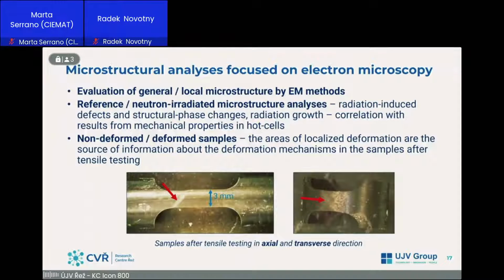And going to the microstructural support, which is focused on electron microscopy studies, this is like the last part of evaluation. So we compare the reference and neutron irradiated microstructure analysis and evaluate the radiation-induced defects and structural phases, and as well the radiation growth, and it correlates with the results from the mechanical testing. We as well compare the non-deformed and deformed specimens so that we notice the areas of localized deformation, and these areas are the source of information. There we study the deformation mechanisms. We evaluate the general and local microstructure by electron microscopy methods.